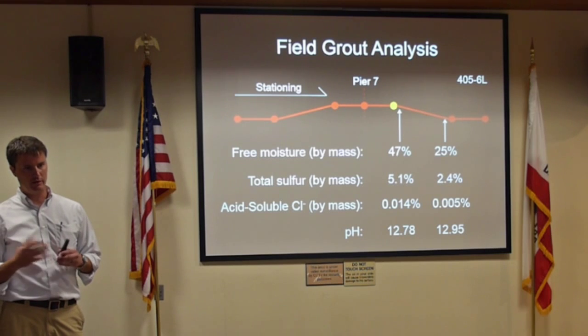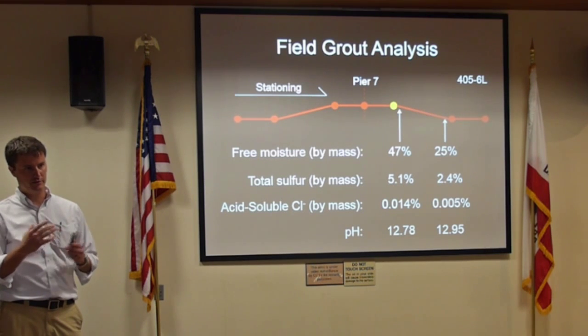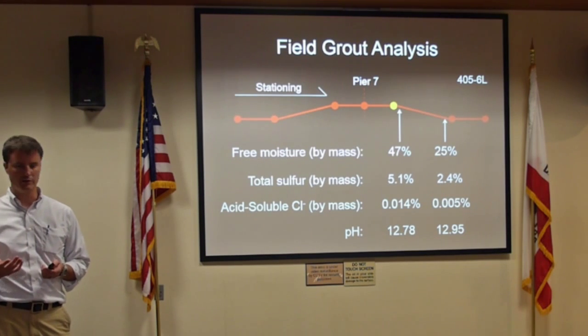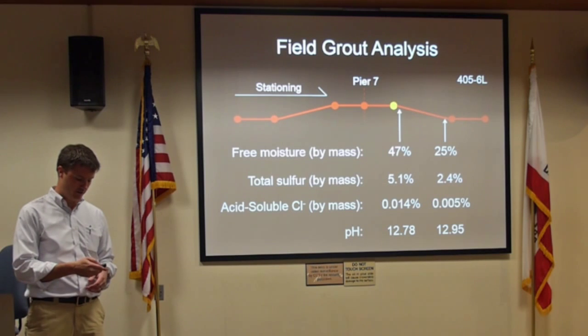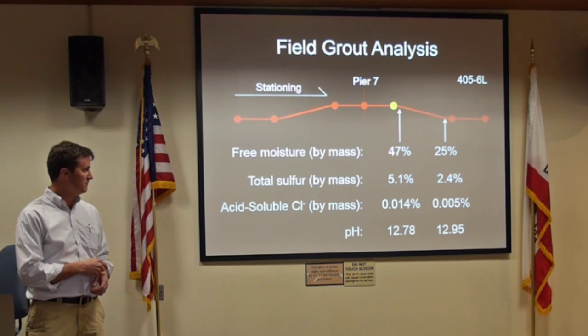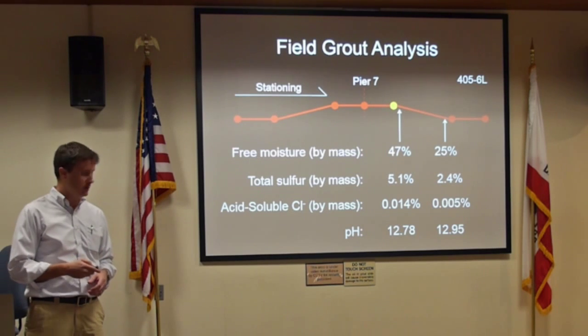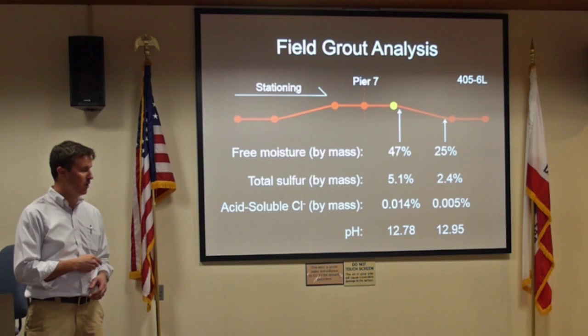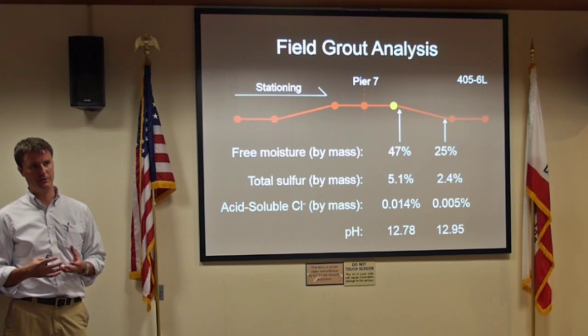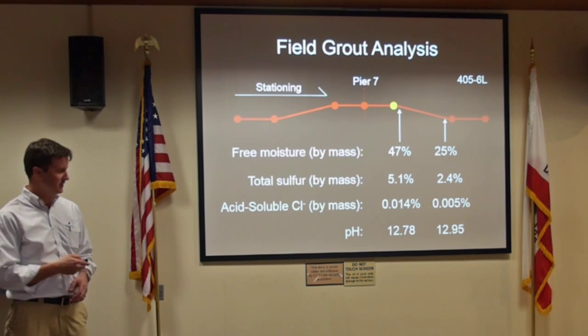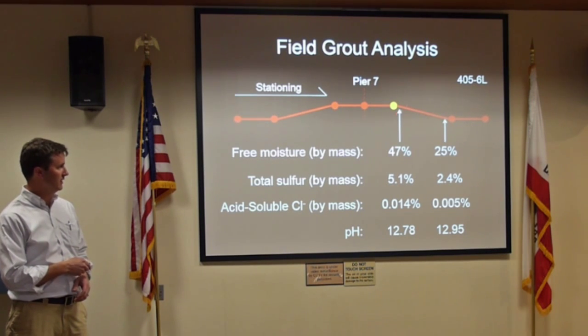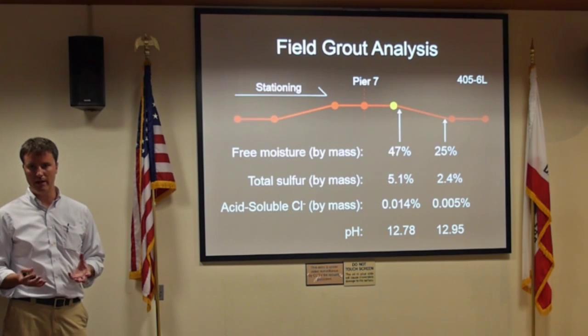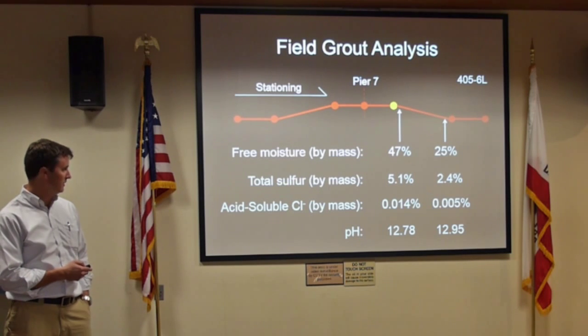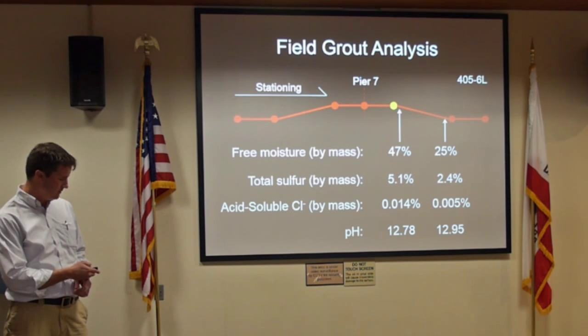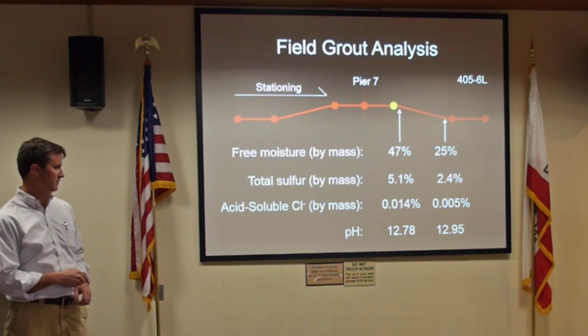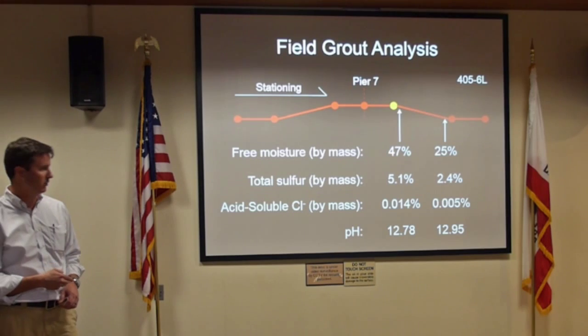As seen on concrete placements, after a little while, eventually bleed water comes up as the material starts separating a little bit. It's a similar phenomenon in these prepackaged grouts that are used to put in additional tendons. As the material started to segregate, the cementitious material is more dense than the water, and so basically displacing water, and usually ends up with a lot of water and a lot of other materials that kind of went along for the ride and ultimately settled here. And as it started downhill, it left a void here once that water desiccated back uphill, downhill from the high bank. So as the water moved, it transported all these materials, and that's why you ended up with higher concentrations of sulfur and chlorides at the top area.